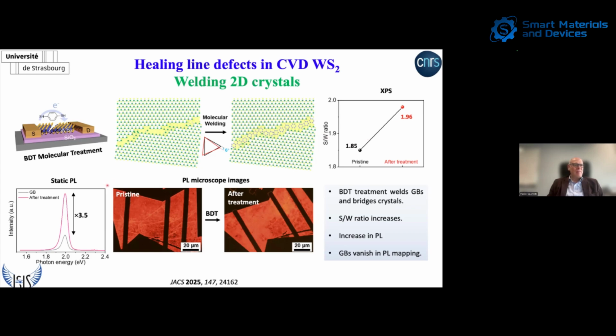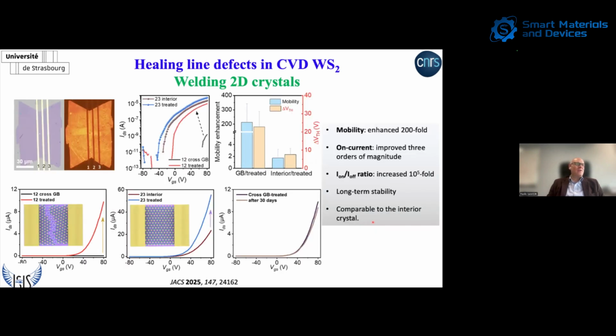And now the effect can be both on the optical and on the electrical characteristics. You can see here that as soon as we heal the line defect, we have a 3.5-fold increase of the photoluminescence in our film. And the grain boundary is not observed anymore upon this kind of healing with the benzene dithiol. And likewise, you can also observe that we have a major 200-fold increase of the field effect mobility, and a 10 to the power 5-fold increase of the on-off ratio.